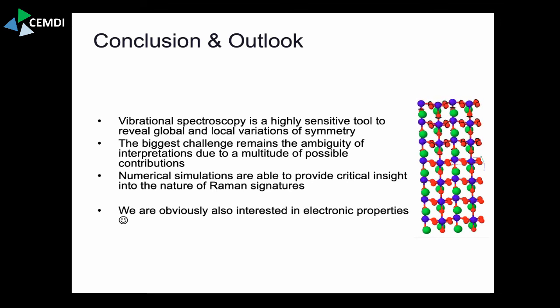That means the surface will react with itself. You know that silicon has these, what is it, 5x5 or 7x7 reconstructions, because you've got these dangling unsaturated bonds, and if nothing else comes, the surface will simply react with itself and create different symmetries. But this is actually part of the hope that we have, that the technique would be able to sense these surface reconstructions. Otherwise, you would need to go into ultra-high vacuum and then hope that you get sufficient resolution and conclusive data that you actually see this reconstruction by symmetry breaking.